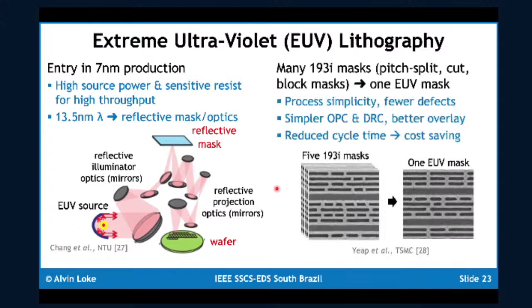One of the beauties of using EUV, and this is what was done more so by TSMC, is really for process simplicity and cost reduction. If you try to pattern very fine features, it's not uncommon to have as many as 5 masks, 193 immersion masks, with a combination of several pitch split line masks, even cut masks or pitch split and block masks. You can reduce all that to a single EUV mask, giving you a simpler process and fewer defects. All in all, you get essentially better cycle time and cost savings.